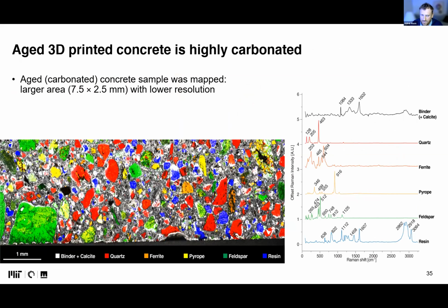And here I will leave you with this image of 3D printed mortar, where we clearly see huge carbonation. This peak of 1084 is in the range of calcite, and of course there are many phases that are formed, with little peaks that can be analyzed that are aragonite or other polymorphs, but everything can be clearly contextualized in such a complex material.